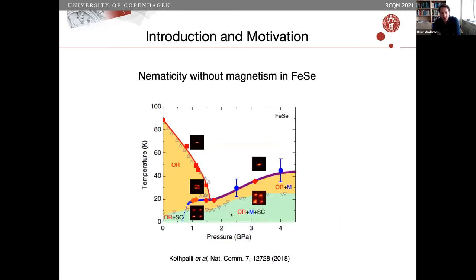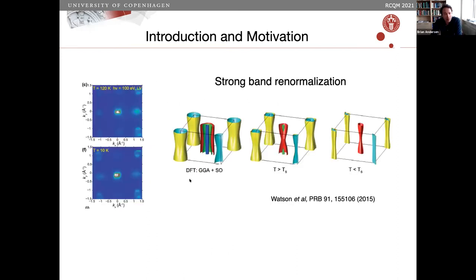We are fascinated by iron selenide because it's a very flexible material — you can tune T_c and the system goes superconducting from this nematic phase. We still don't know what is actually the detailed nature of this nematic phase. Another fascinating aspect is the origin of this very strong band renormalization. What comes out of DFT — and there are many different versions of it — but the standard one in the literature gives way too large pockets, too large a number of pockets, and strong renormalization compared to what's measured in the actual low temperature nematic phase.